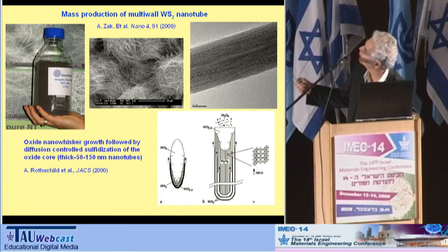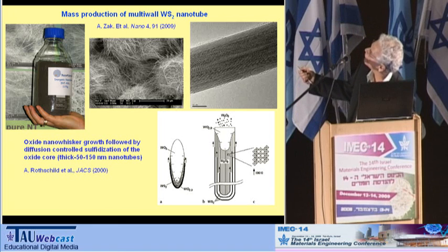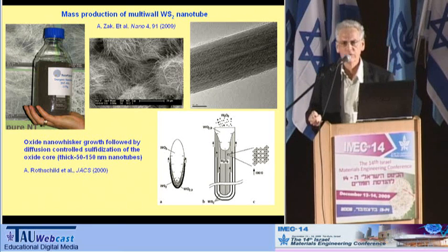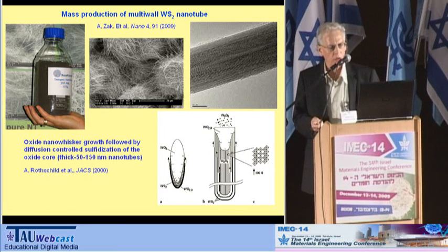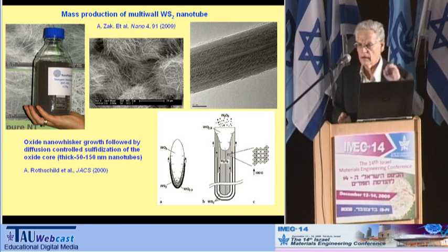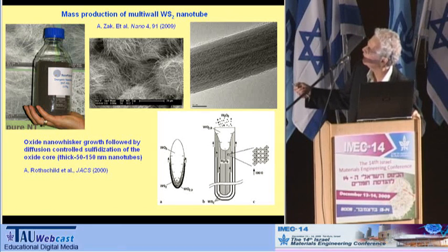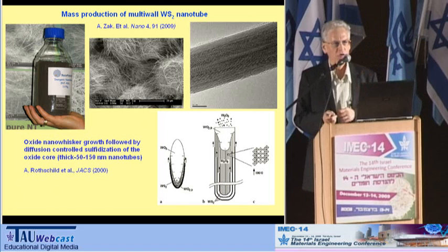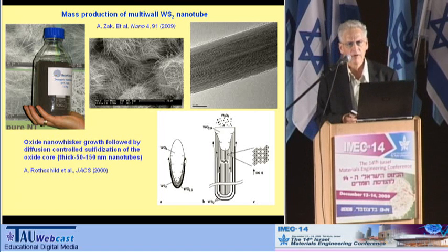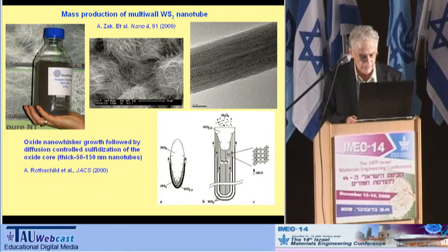And you see these nanotubes have more layers. They are a bit thicker. They are about 30 to 50 and up to 100 nanometers in diameter, but very long and very strong and very perfect in shape. And therefore, their mechanical properties are very desirable for many, many applications.